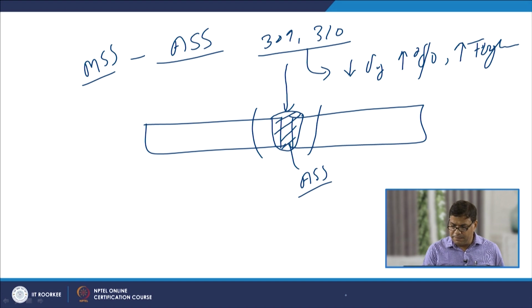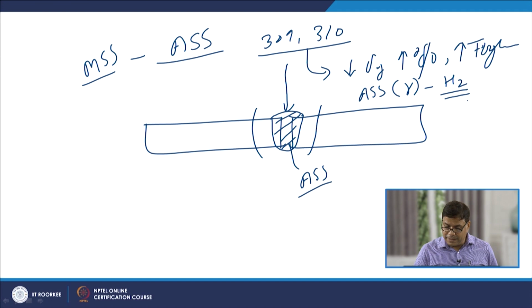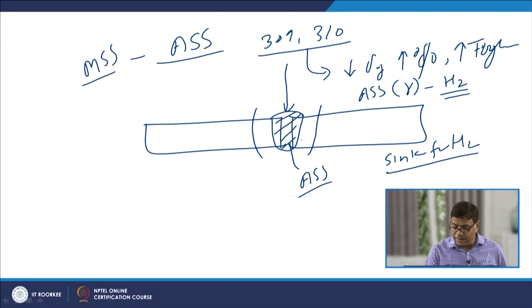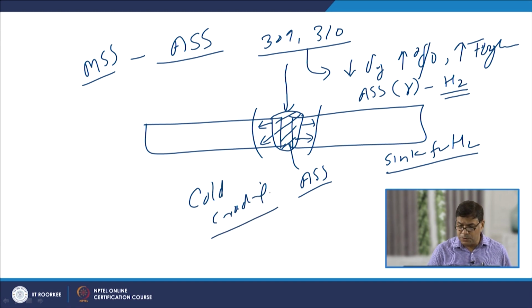At the same time, the austenitic stainless steel has austenite, which shows greater solubility for hydrogen. So, the ASS weld metal acts as a sink for hydrogen, and it does not allow the hydrogen to get into the heat affected zone as well as the base metal, and that is why the cold cracking tendency is reduced when the austenitic stainless steel fillers are used.